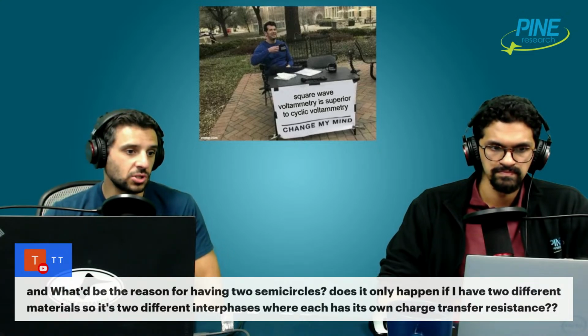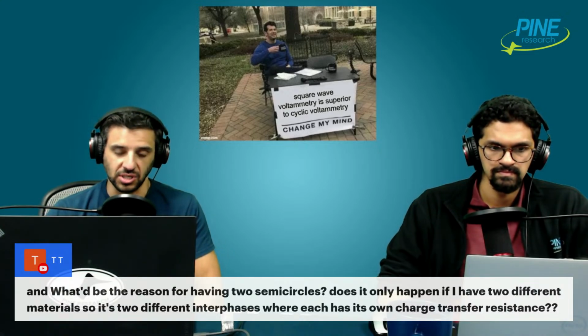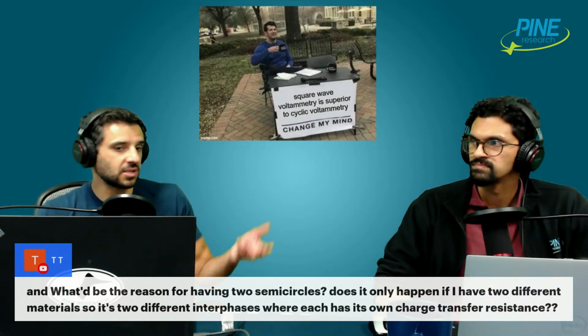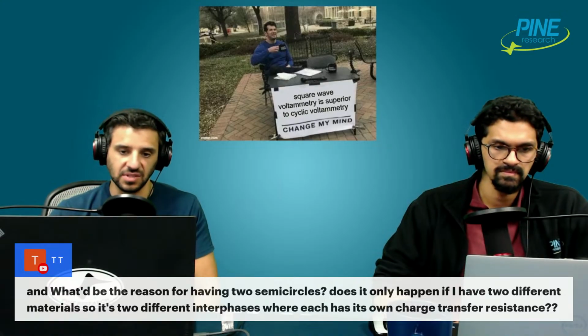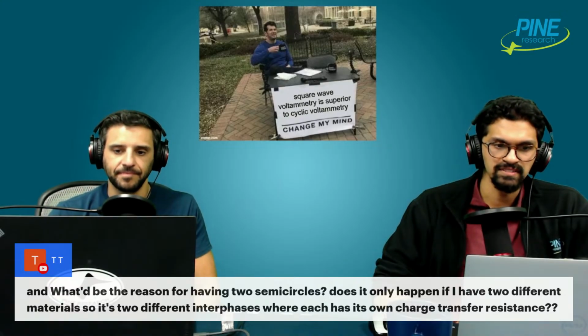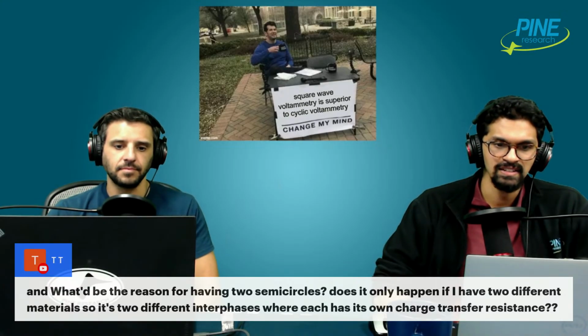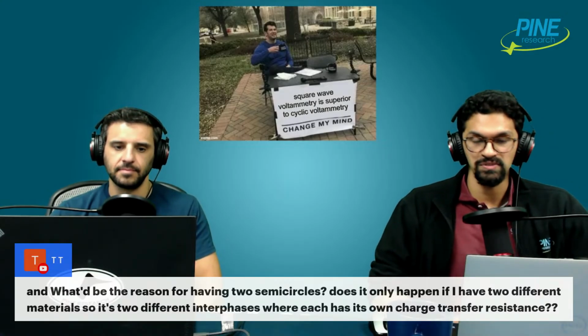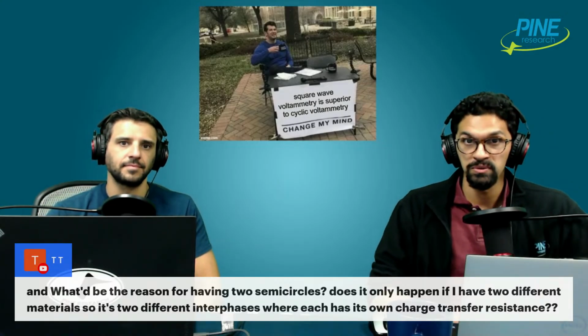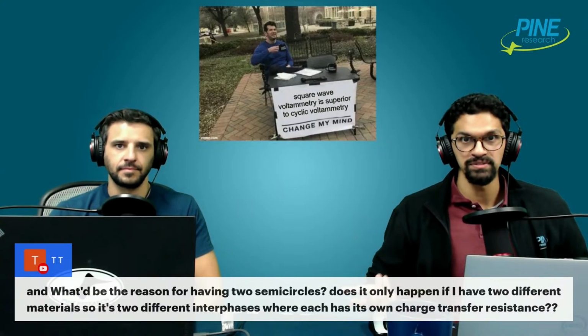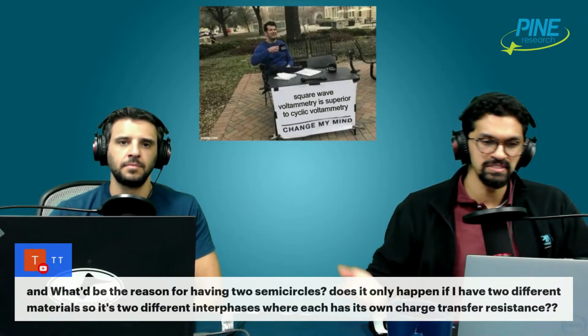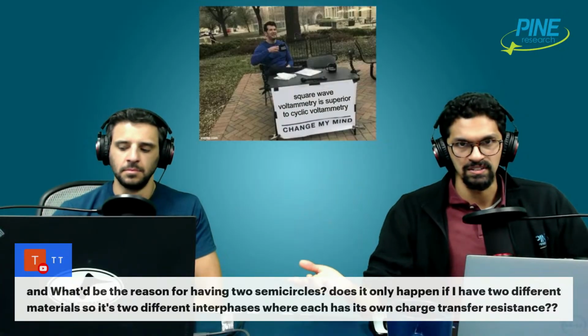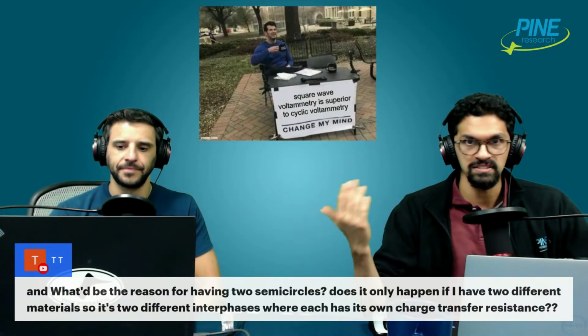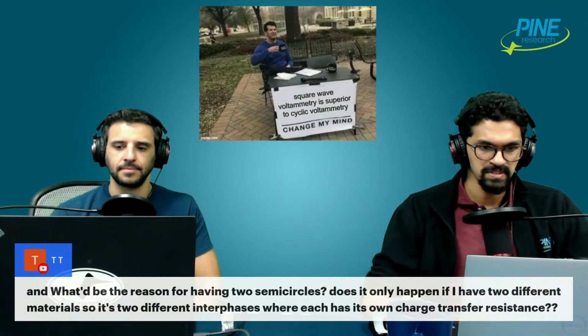But it could also be 2 different processes on the same surface that just happen to occur at different speeds. Like Alex said, they're just 2 different time constants. There's just 2 different processes on the same metal surface that can also happen. And it may even be the case that they have their own charge transfer resistance, but they may also have their own capacitance. So those values can also be different. So in addition to charge transfer, consider the capacitance at that interface that would also cause the semicircle.